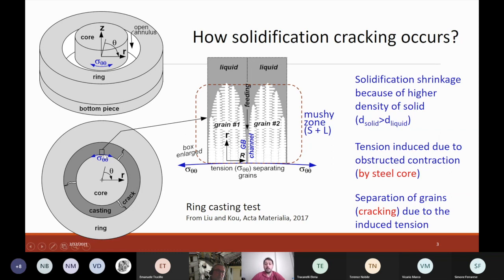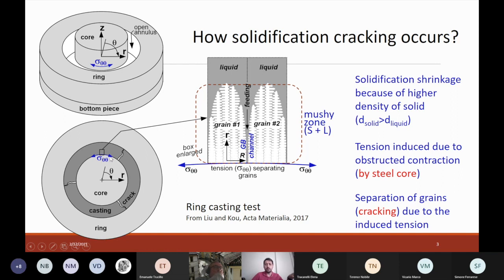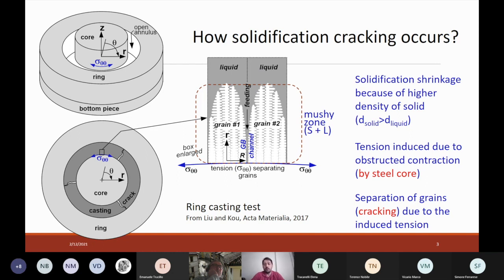Let me show you what's going on at the micro scale. This is taken from near the core wall. During solidification, we see columnar dendritic grains growing in the vertical direction, nucleating from the core wall — heterogeneous nucleation. The sigma theta theta tensile stresses are separating these two dendritic grains from each other. If you don't have grain refiners in your alloy, you see columnar dendritic grains. If you have grain refiners, they are usually resistant to cracking. This is the case without any grain refining.